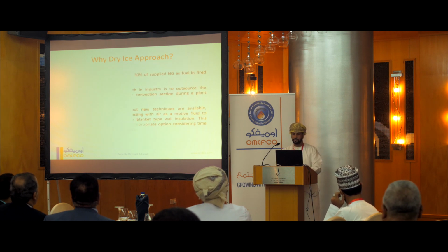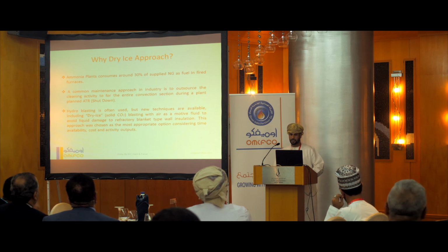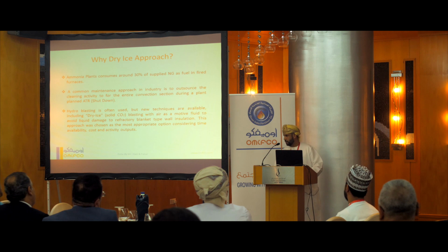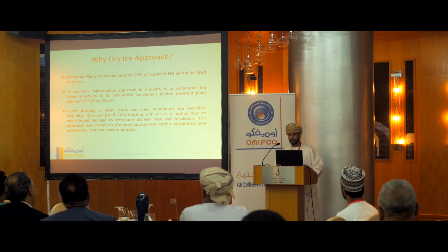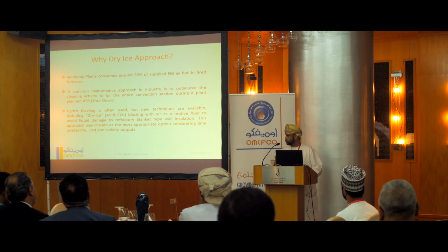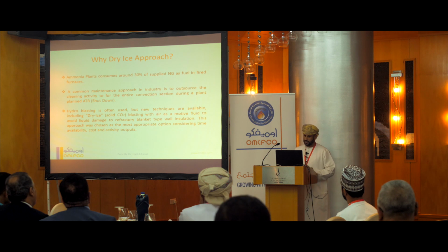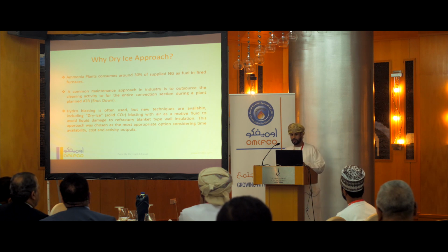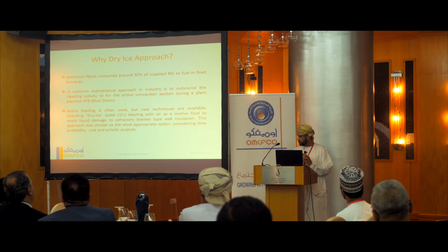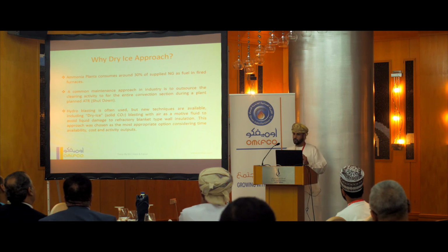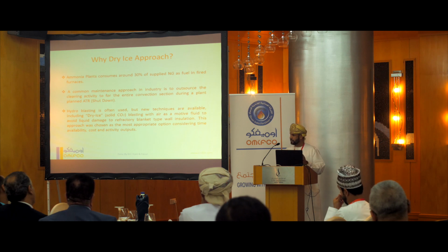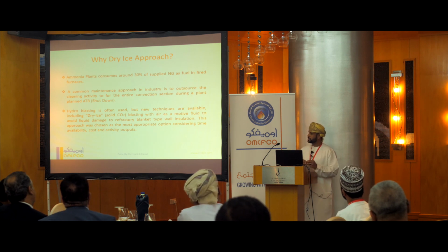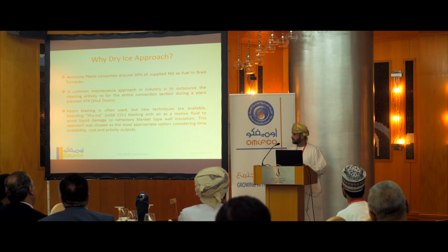Now we'll discuss the main issue of our case study, which is dry ice. Why dry ice? Before, we used sandblasting and even a water jet to remove the deposit in the tubes. But as we know, the ammonia plant is consuming around 30% of the total plant's NG as fuel. So if we can reduce this fuel consumption, we can save energy and get more production. That is why we use dry ice cleaning, to get maximum production or reduce the fuel gas.